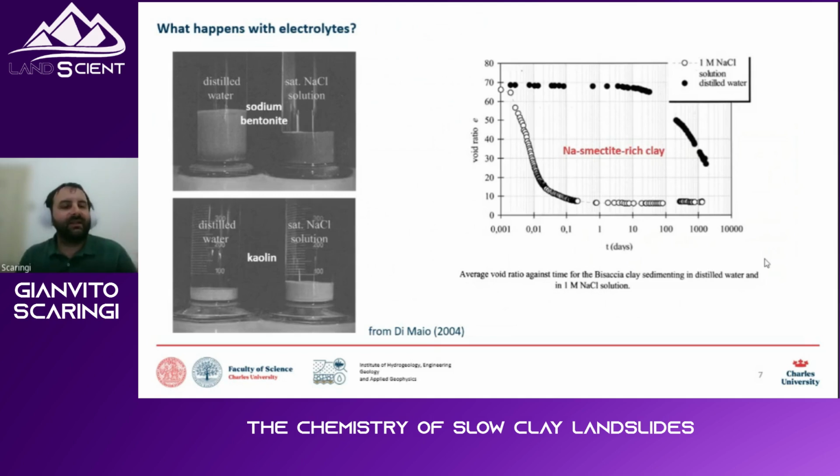which could represent a condition like seawater. These are marine clays that are formed also in marine environments. So if you take a sodium bentonite in distilled water, which could be representative of condition at the bottom of a very pure high elevation lake, it settles with a high volume. That's because the diffuse double layers are very nicely developed, because there are no ions counterbalancing the charges of water.